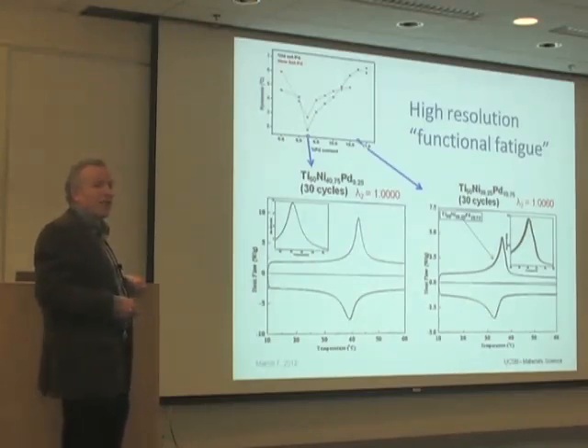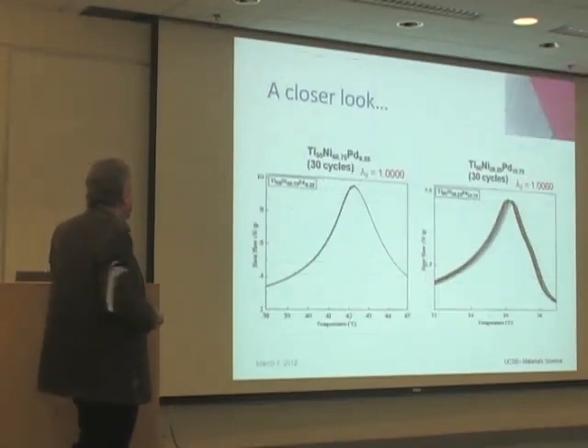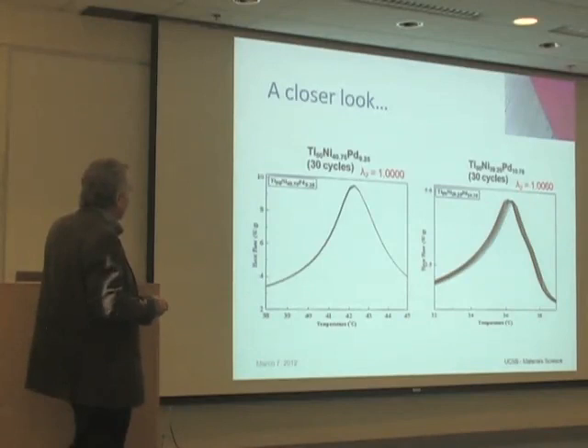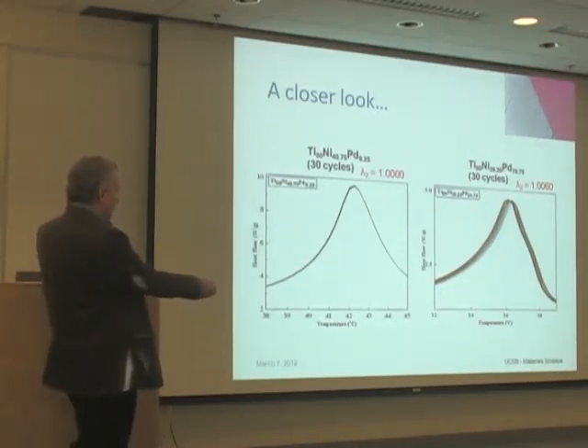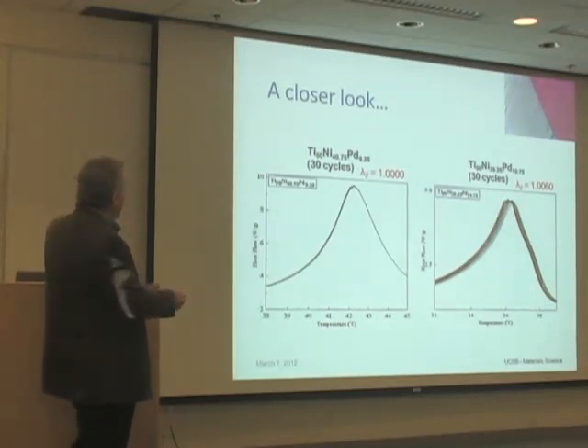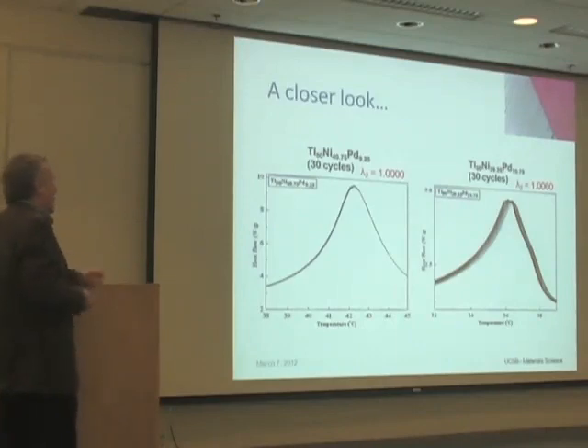There's a blow up of, and you can see again, having lambda 2 very close to 1 is quite important for that. And so one could think that for this alloy, there's still a small transition layer left and some stress in that layer. Maybe the stress in that layer is sufficient to nucleate dislocations. That's creating damage in the material, and that's responsible for this migration. And when lambda 2 is 1, you remove that elastic transition layer. So that's a natural hypothesis, but not proven for this case, for any case.